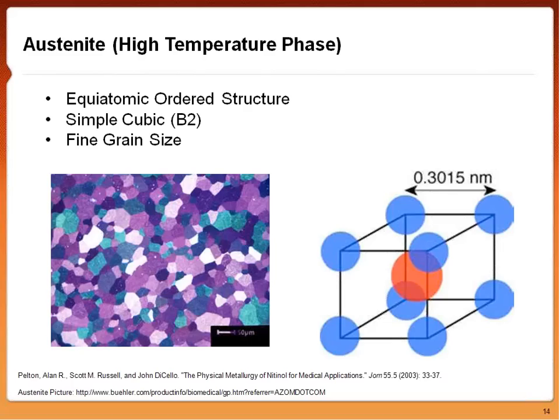When we look at the crystal structure of the austenite phase, it's an equiatomic structure. It's a simple cubic. If you imagine that the red atoms at the center are nickel atoms, and the blue atoms are titanium atoms, for every nickel there is a titanium atom. It's an ordered structure. You can see that this ordered structure produces a fine subgrain network. This picture is an optical transmission electron microscopy image, and you can see the scale is very small, meaning it has fine subgrains due to its ordering. All the angles in the crystal structure are at roughly 90 degrees.